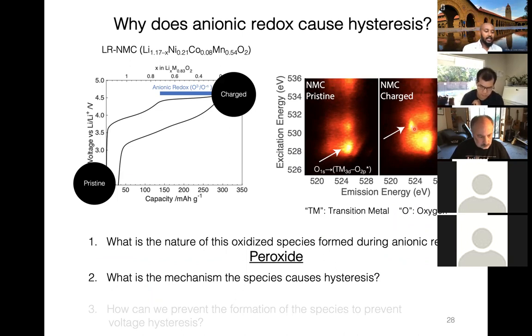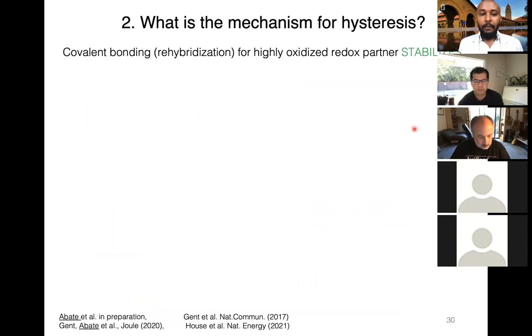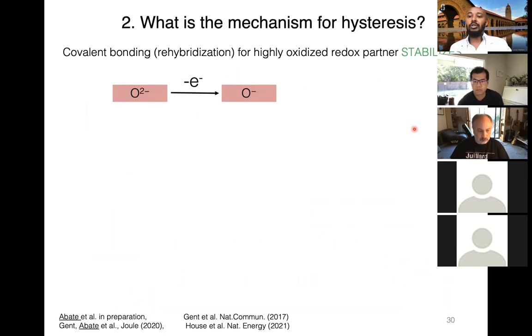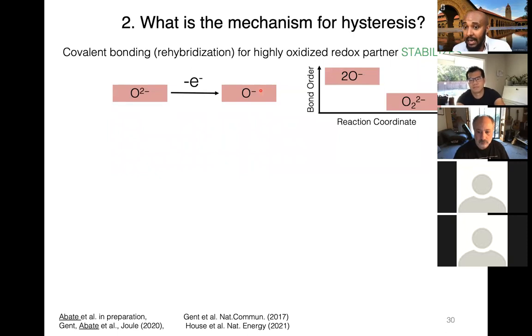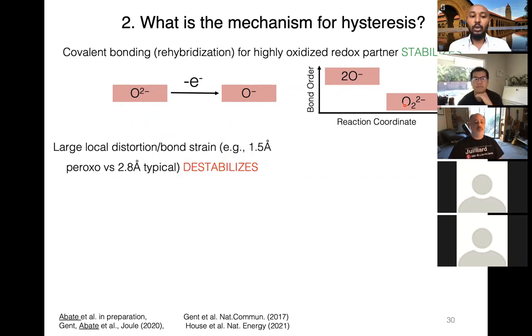So to understand this mechanism, I'll again go back to the first thing that I was saying about the chemistry behind ionic redox. What happens when you have ionic redox is that we are removing an electron from an oxide O2- state in the pristine to an O- state. However, the O- state is not stable thermodynamically. Therefore, we end up forming oxygen-oxygen bond lengths close to 1.5 angstrom. It happens to be the peroxide dimer. And this stability from the point of thermodynamics is what's also leading to forming this short covalent bond that's causing a